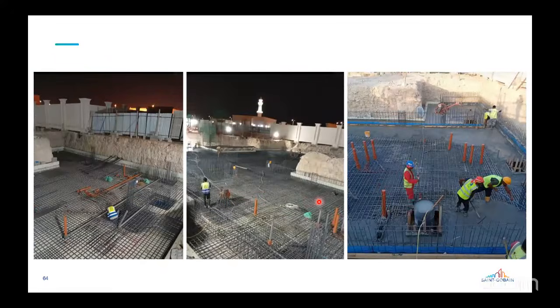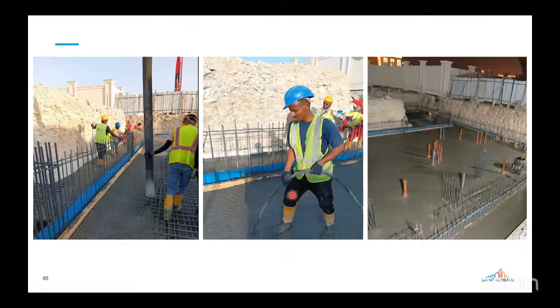Here you can see a lot of penetrations and pipes: pressure release pipes, drainage pipes and the PRP pipes. All these are embedded into the waterproofing system, and we do proper sealing using an epoxy grout around all these pipes. Finally the concreting is done up to half the thickness of the waterstop. The concrete is poured directly onto the membrane, and because there is an adhesive on the top side of the membrane, it bonds to the freshly poured concrete.